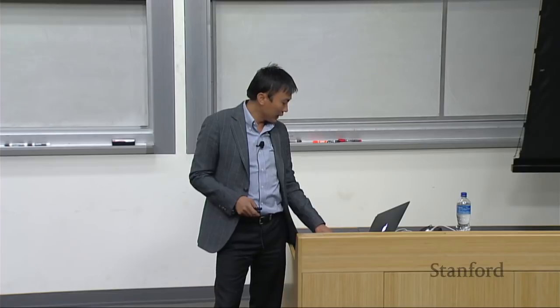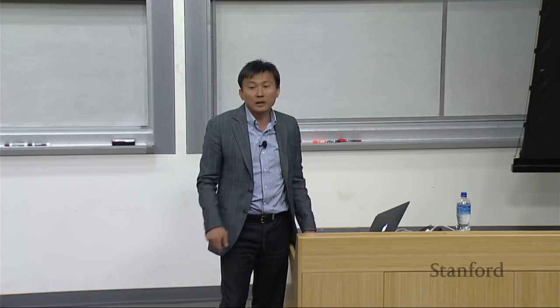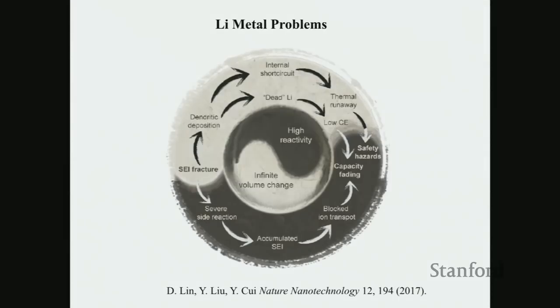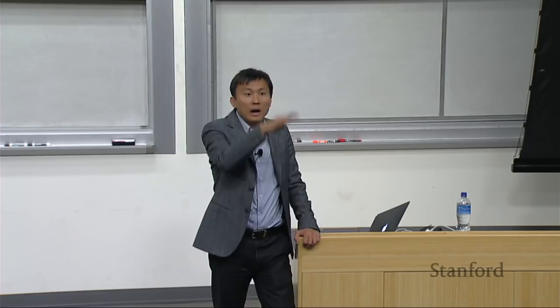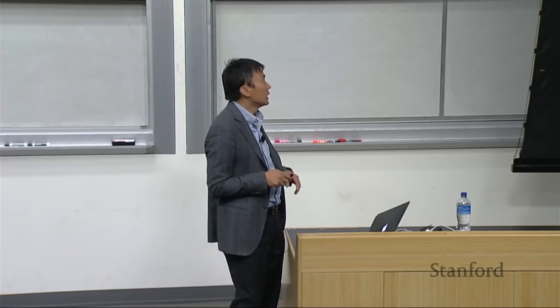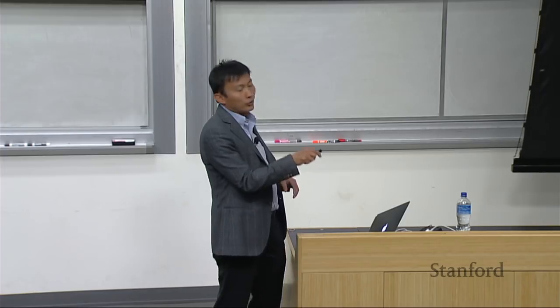We have summarized all this learning in this perspective paper in Nature Nanotechnology. We combine what people learned in the past 50 years and what we learned in our group, and we pointed out to the community that the root cause of the problem is actually in the center. Outside is the surrounding phenomenon. The central problem is the high chemical reactivity of lithium, coupled together with relatively infinite volume change during plating and stripping, up and down. This process makes it very hard to handle. So this causes all this problem outside.